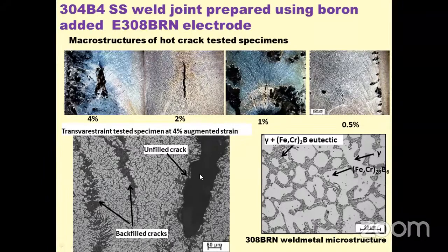So here we can see the macrostructure. We can see that the finer cracks are getting backfilled because it is a borated electrode. It has around 1 weight percentage of boron in it, and it also forms eutectics and forms the liquid that can backfill the cracks. But the liquid volume that is formed in this borated electrode is very limited. So it cannot backfill all the cracks as in the 304B4 base metal we have found. Here we are seeing unfilled cracks that are open at a higher augmented strain.